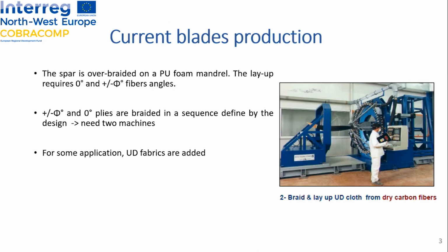A few words about aeronautic blades production, which is already done by Euramaterials. You can see on this slide the spar part overbraided on a polyurethane foam mandrel. To produce the blades, the layup requirement is 0 degree, so unidirectional, and also plus and minus braid angle for the bias direction.